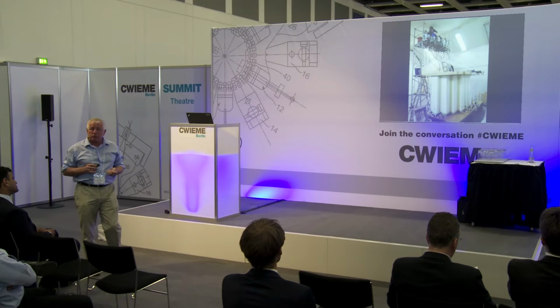The blocks are then machined and then assembled and glued into major assemblies. So this is a glue-up process for a number of blocks for a part of Deep Sea Challenger. The glued-up block is then machined. We actually had dye penetrant on this surface. We did have an issue, but we resolved what it was, and it just meant that particular piece was a little bit shorter than the rest of it. We just built it up with another piece. But we ended up machining quite complex shapes. You can see the join lines of the glue for each particular block, and this is one of the lowest sections of the sub. There were about 6 sections involved by the time we got the sub to full length.